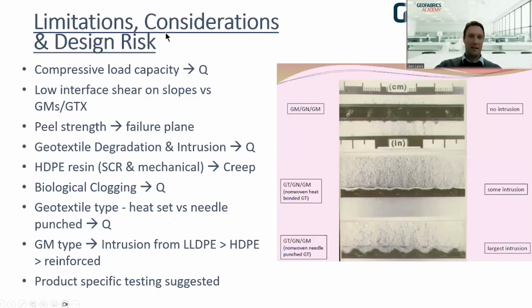In terms of limitations, considerations, and design risk, generally we consider compressive load capacity. The higher the compressive load, the less the flow rate would be. Low interface shear on slopes. It changes with what your laminated material is. Sometimes you obviously have naked nets, and sometimes you've got a geotextile on the net, so you need to consider how that performs on your slopes. Peel risk: is the geotextile going to peel off and slide as you place fill over the top? And I'm just really reeling off some considerations more than anything. Geotextile degradation, covering before it starts to degrade with UV, and you're obviously going to get some intrusion of the geotextile depending on the thickness, so that will impact your flow rates.